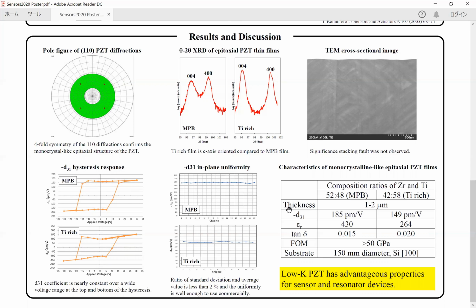These figures show the uniformity of the D31 coefficient for several devices cut from a linear array of positions across the diameter of a wafer coated with the epitaxial PZT film stack. The ratio of standard deviation and average value is less than 2%, and the uniformity is well enough to use commercially. This table summarizes the characteristics of two kinds of monocrystalline-like epitaxial PZT films.